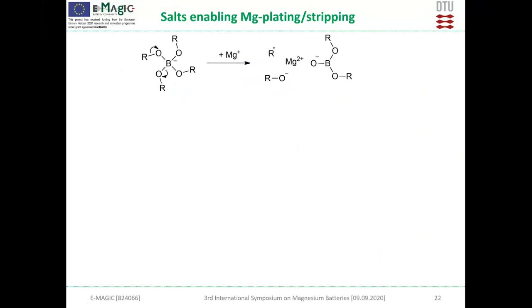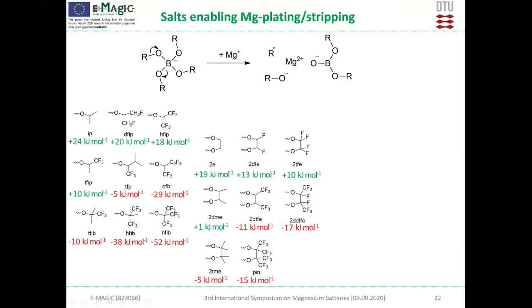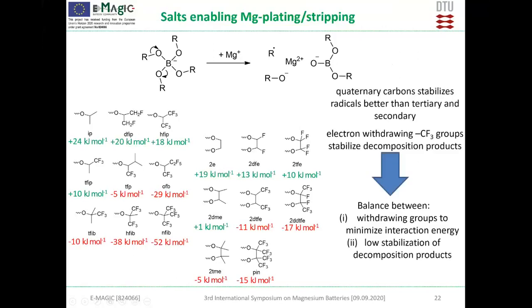the decomposition, we found out that this mechanism of breaking this bond and this bond is the weakest point of the salt when we add this magnesium plus. So we studied this for all of the ligands and found out that there is quite a clear connection between the structure and the stability, because if we have a lot of groups connected here to this carbon, it will stabilize the radical formed here. And if we have a lot of withdrawing groups like CF3, we will have stabilization of this species. And all of these effects are just moving the reaction in this way, making it easier to